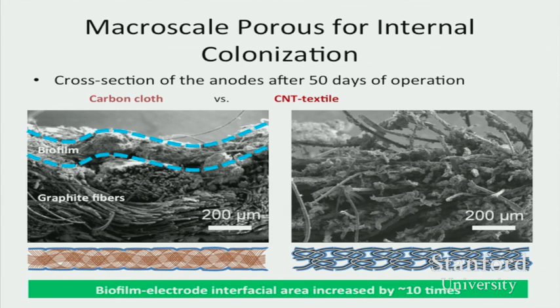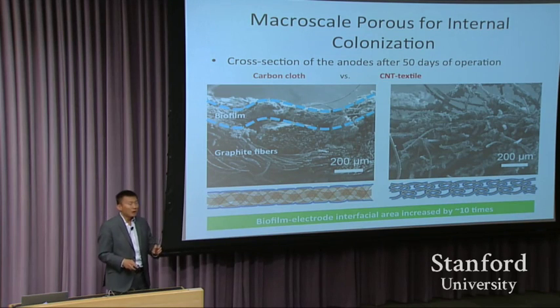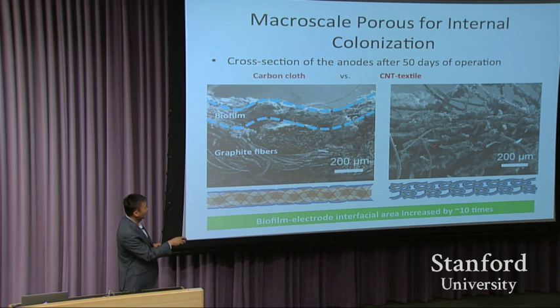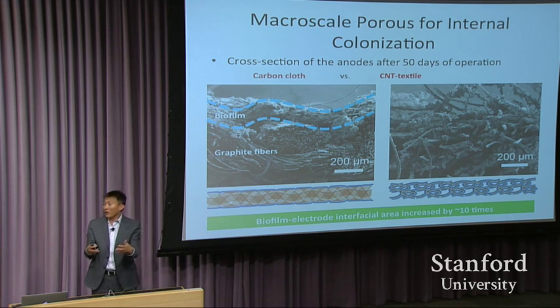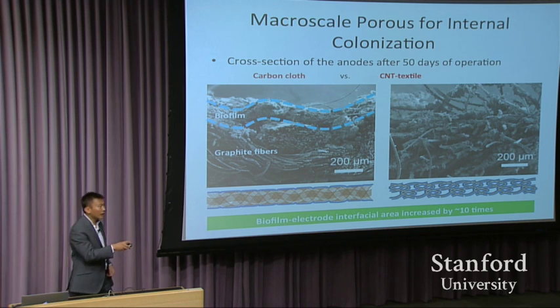And then we compare, the left side is the carbon cloth, the state of the art, and the right side is our carbon nanotube textile. And in this carbon cloth, the fibers are very densely packed. You see most of the microbes forming this biofilm coating on the top surface. But with the textile right there, because it's highly porous, with big pores in there, the microbes can actually go inside and grow very deep. Each of these fiber surfaces is now covered by microbes. Now you can have a lot more microbes in close contact with this conducting textile fiber. So these provide a lot more microbes to do the job.